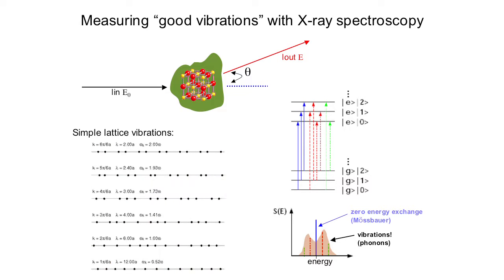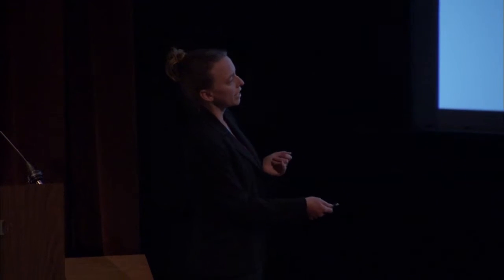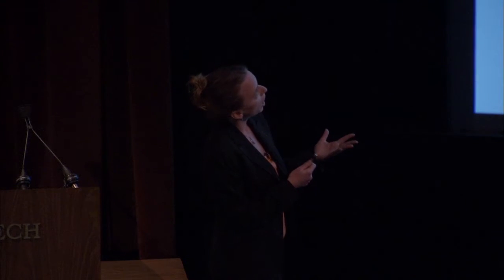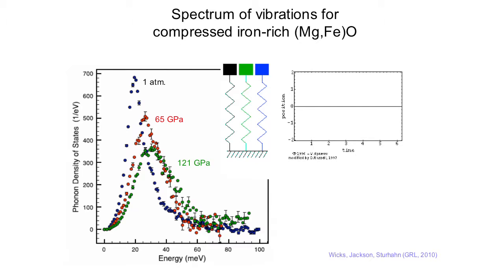And in this energy diagram here, it just shows that if the state is the same, so a G0 to an E0, that's considered no energy exchange, and that's in the blue line here, also called the elastic scattering. And every other mode here is depicted away from this energy. It's also called an inelastic scattering process, but that is exactly what is being measured by the interaction of these vibrations. So if we can analyze that spectrum, then we can know what are the P and S waves of this material, in addition to many other thermodynamic properties.